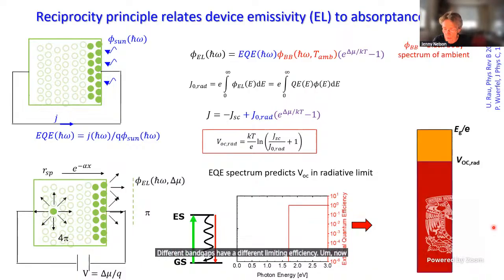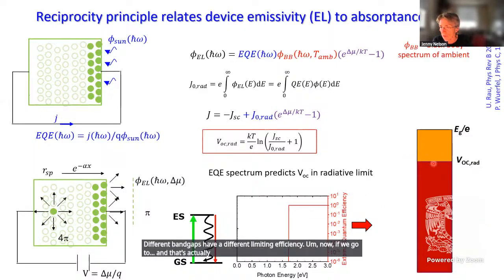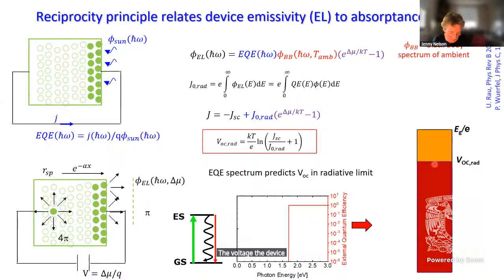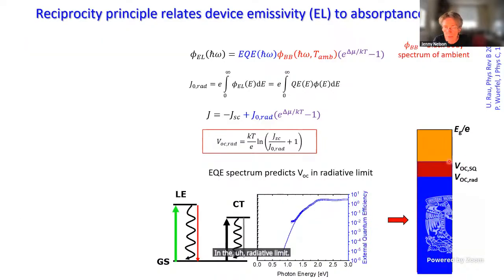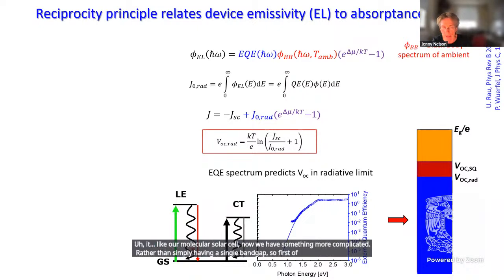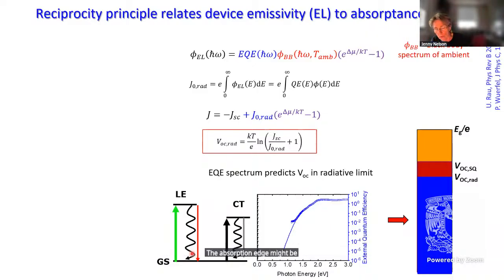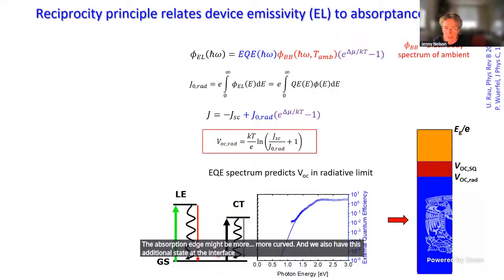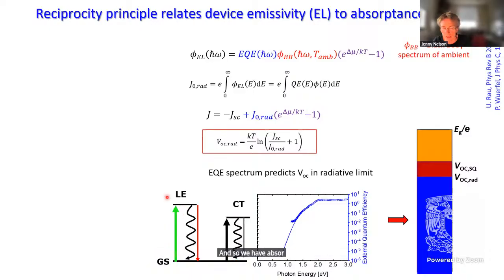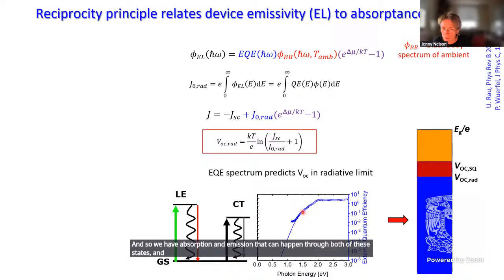Now, that Shockley-Queisser limit would correspond to the voltage the device would deliver being the same as the one that it gets in the radiative limit. Now, if we go to a real material, like our molecular solar cell, we have something more complicated than simply a single band gap. First of all, the absorption edge might be more curved. And we also have this additional state at the interface, the charge transfer state. And so we have absorption and emission that can happen through both of these states. And that leads to a spectrum that's no longer a nice step, but it's quite curved.